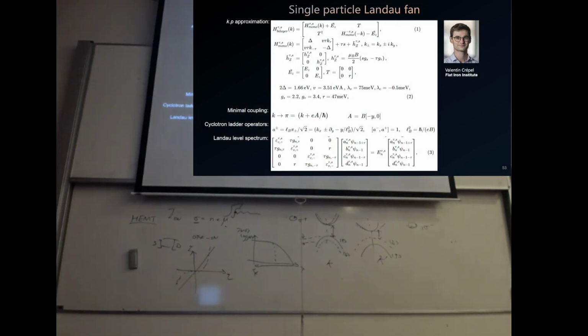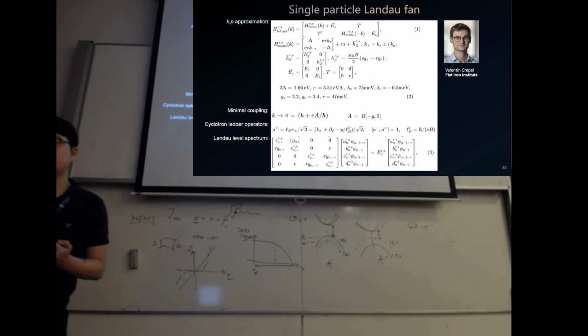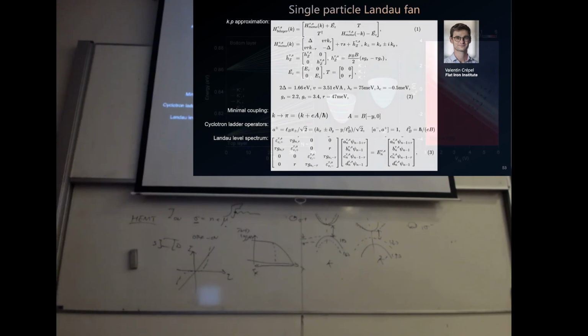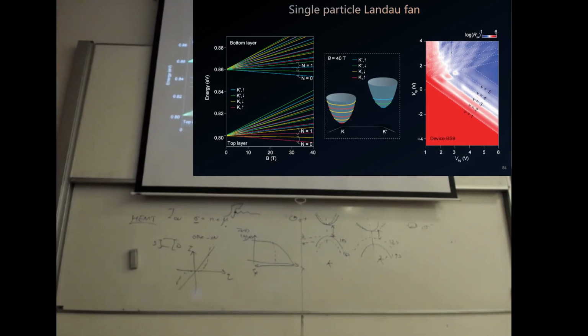And our theoretical collaborator from Flatiron, Valentin Krepel, did some calculations of a single particle Landau fan of bilayer MoS2. Using this k·p model, at the end he got this kind of calculated Landau fan. There is one specific point we have to emphasize: if you look at the color of the Landau levels, they are only yellow and red, which is only 1K, so they come from the same valley. That means the lowest 4 Landau levels are valley polarized.